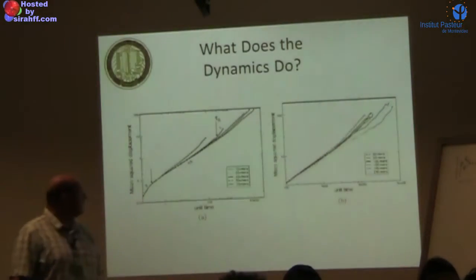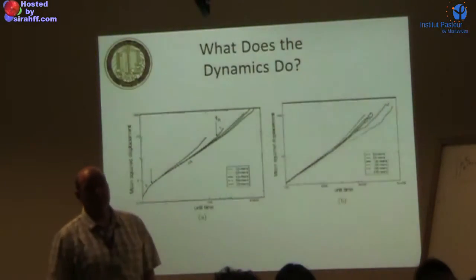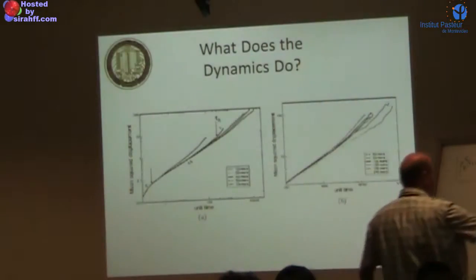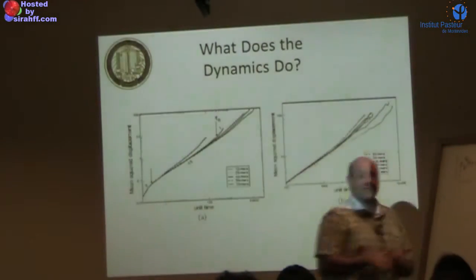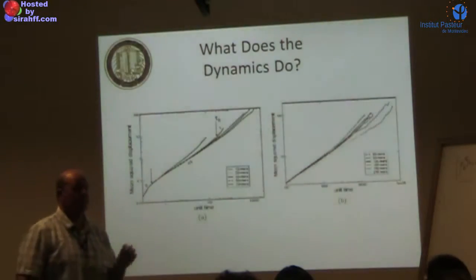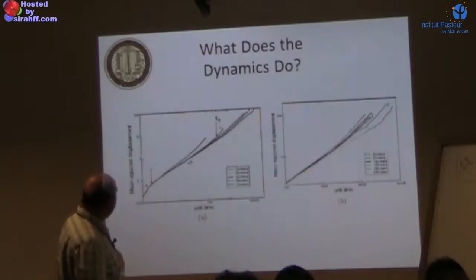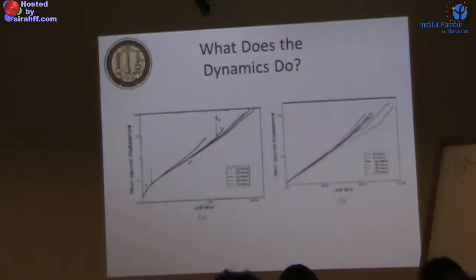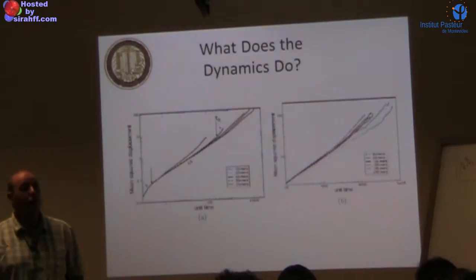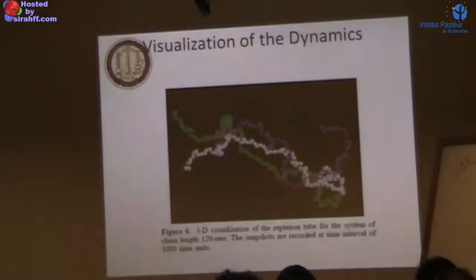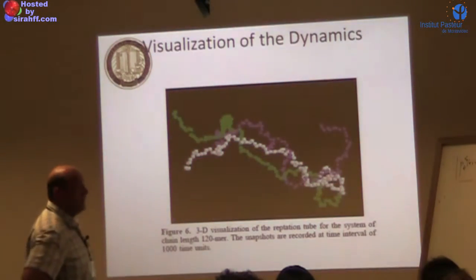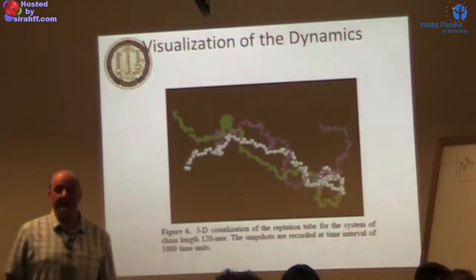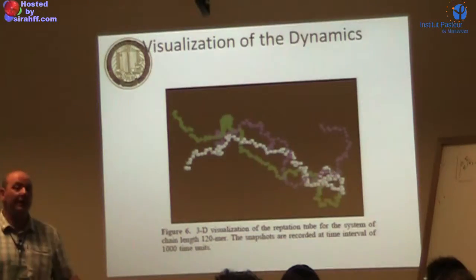This is a dynamics comparison from work done a few years ago — mean square displacements. We measure the mean square displacement of the central monomer, not the center of mass. We did this as a function of chain length and recovered what we expected from polymer physics, again with the correct prefactors. So relaxation times here are well beyond microseconds.